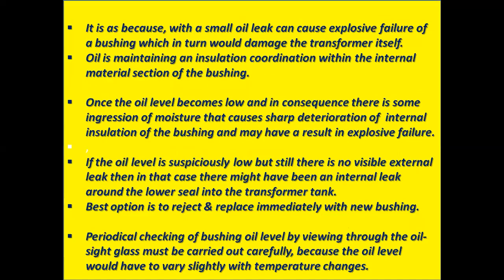It is because even a small oil leak can cause explosive failure of the bushing, which in turn would damage the transformer itself. Oil maintains insulation coordination within the internal material section of the bushing. Once the oil level becomes low, and in consequence there is some ingression of moisture, that causes sharp deterioration of the internal insulation of the bushing and may result in explosive failure.